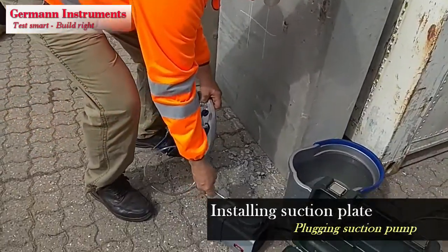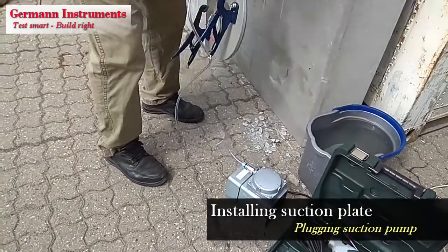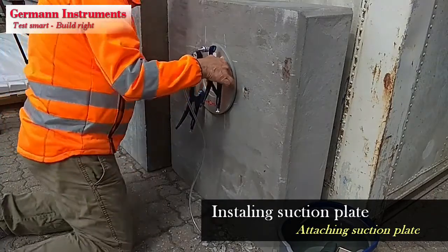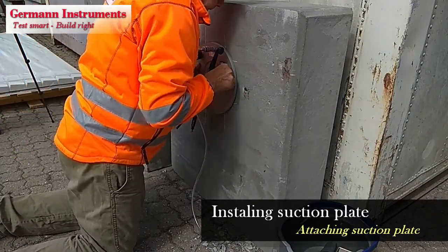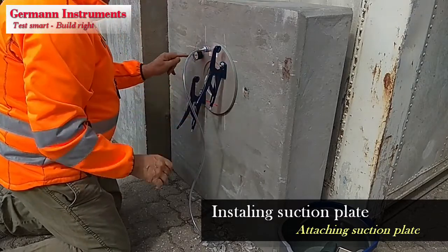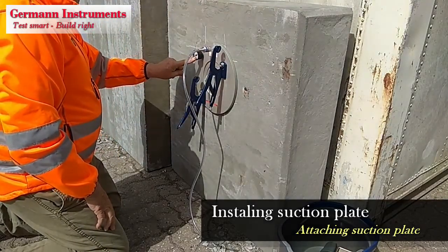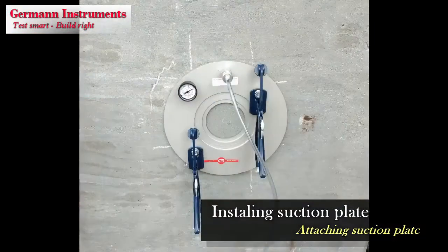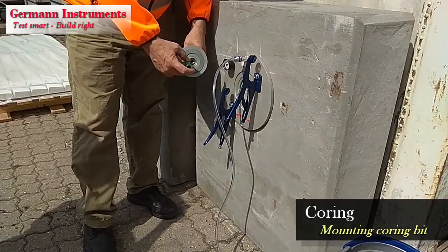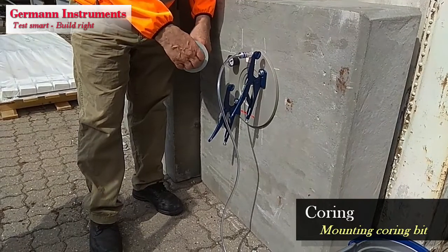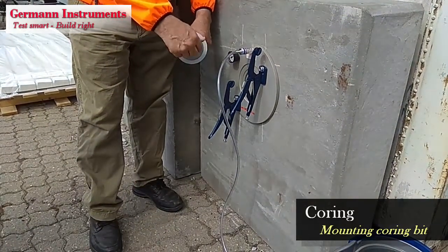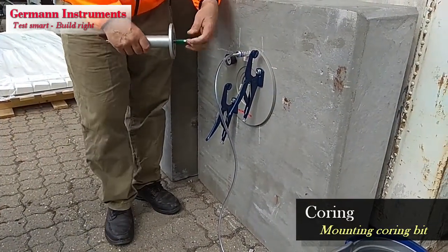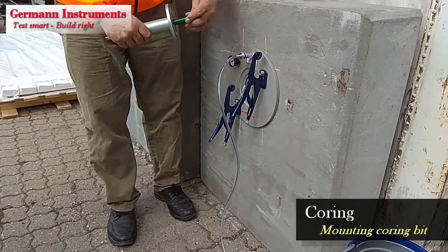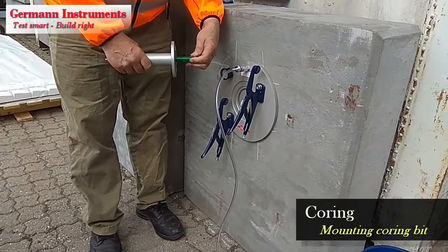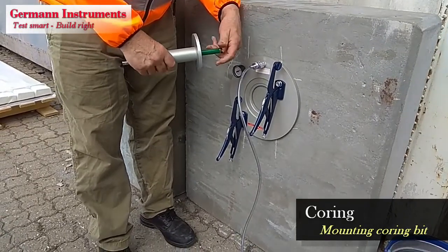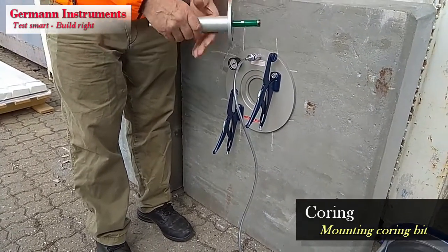The clamping pliers are attached to the suction plate, loosely, and the plate is connected to the activated vacuum pump. Pressing the vacuum plate against the surface will pull the vacuum to approximately -0.8 bar indicated on the plate's vacuum gauge. Install the diamond coring bit on the shaft of the assembled coring housing. The green coring bit produces the required coring depth of approximately 65 mm. Alternatively, the red coring bit may be used followed up the green coring bit. Unthreading the coring bits from the shaft is easily done by means of two keys.